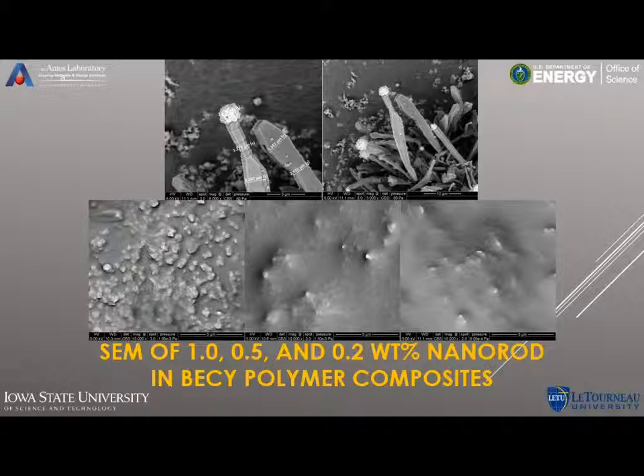These surfaces show the different weight percents that we prepared for the polymer. That is, weight percent of nanorod in the polymer material. And so we've got 1.0 on the far left, 0.5 weight percent of nanorods in the middle, and then 0.2 on the right. And you can tell that these weight percents, which we measured out before we polymerized the material, did still hold true for the solidified polymer.